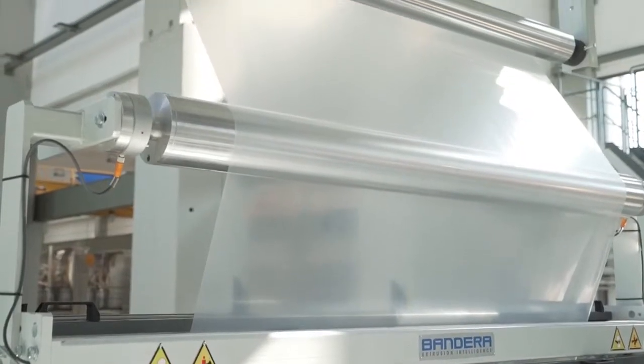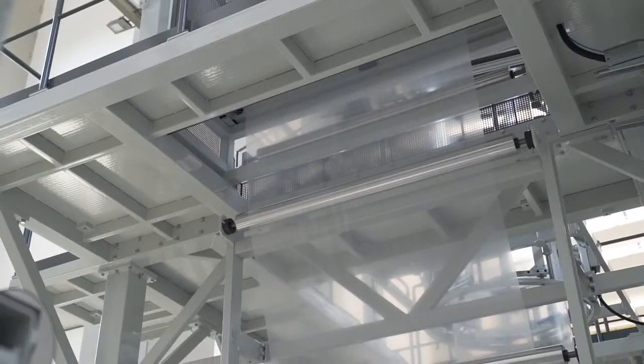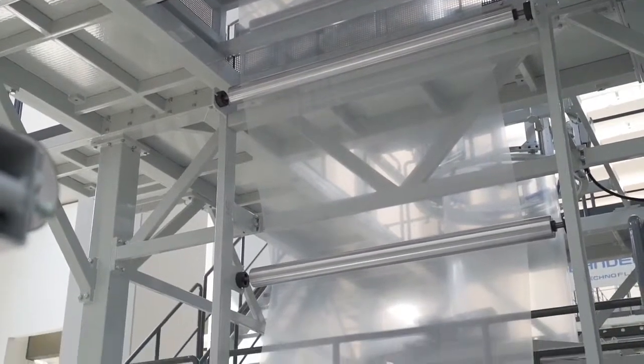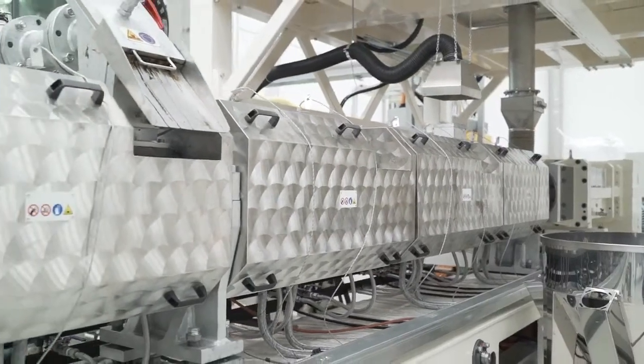Experimentally speaking, outcoming pellets are stable, homogeneous, and 100% reusable to produce new thin films with thicknesses up to 20 microns, while preserving good optical and mechanical properties, closing completely the industrial waste recycling loop. The absolute elimination of VOC and recycled material odor is not achievable in the extrusion, regardless the kind of process. This is why Bandera offers a patented pellet post-treatment to eliminate VOC and complete the upcycling process.